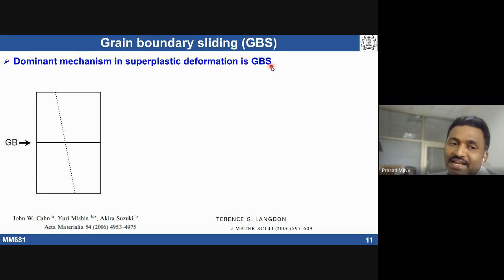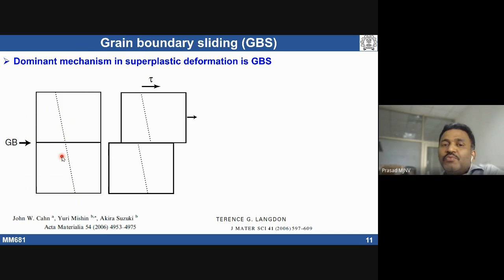grain boundary sliding. For example, assume that I have a bicrystal with a boundary, and you put a very minute micro scratch here. What is the meaning of grain boundary sliding? When you deform the material plastically, a shear component acts on the grains. Across the boundary we see this kind of movement. The grains can slide against each other.